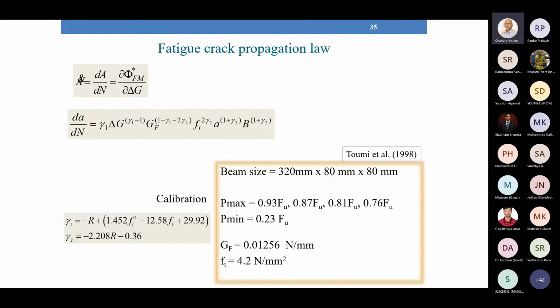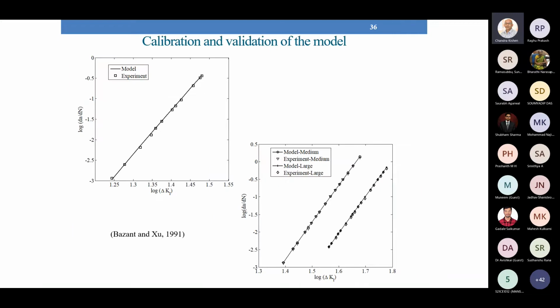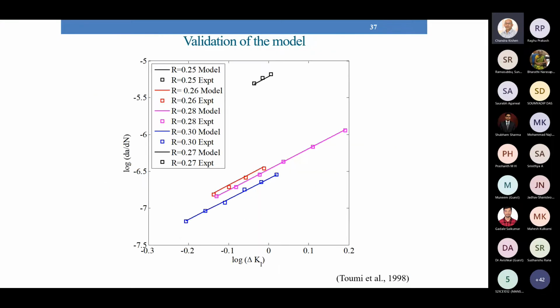from the experiments of Toumi et al. and others, whereas we have validated using the experiments of Bazant and other experimental results which are available, and we see that we get a very good agreement with the model which we have obtained. This is another validation using different experimental results for different R values. Again, we see a very good agreement.